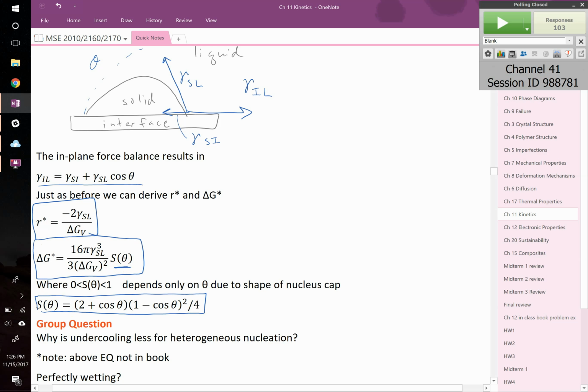Therefore, what we had before was the homogeneous activation energy, this part right here, and you're multiplying that number by something between 0 and 1. That means the activation energy can only ever go down for heterogeneous nucleation. It can only be smaller. The critical nuclei size does not change, but the barrier does change.